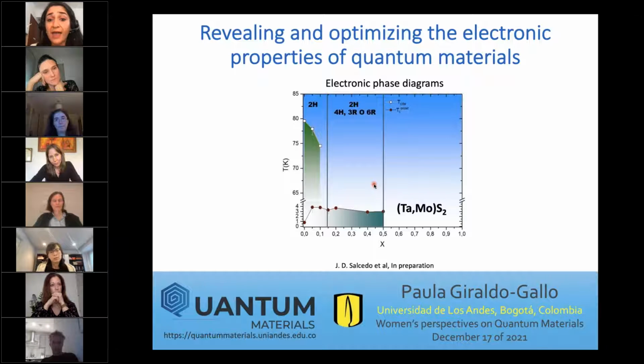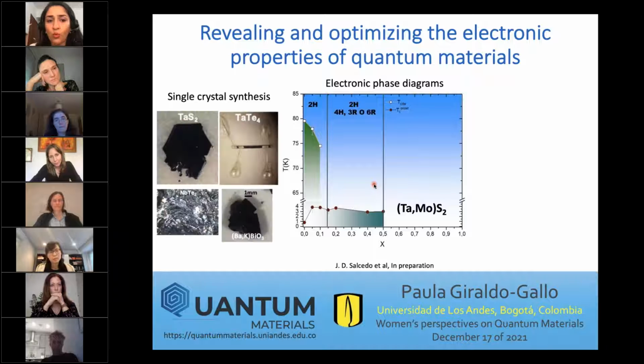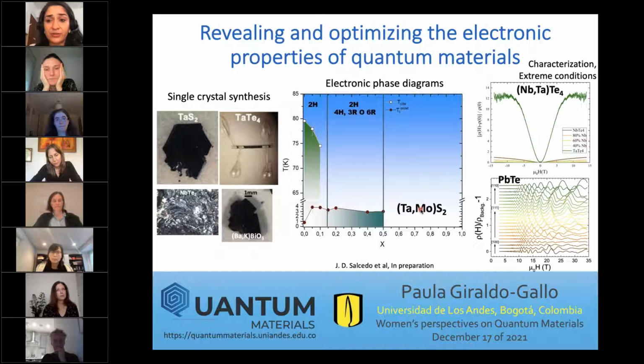So in order to create these electronic phase diagrams, we put a big effort on synthesizing single crystals of this compound. So these are just a couple of examples of the crystals in the materials we are currently studying. And by optimizing and synthesizing these single crystals, we have the flexibility of actually changing the chemical composition and recreating this phase diagram, like for example, doping with molybdenum these tantalum disulfide crystals. And we complement our efforts by characterizing using generally extreme conditions.